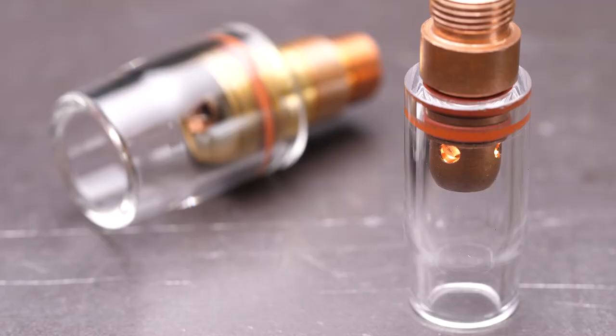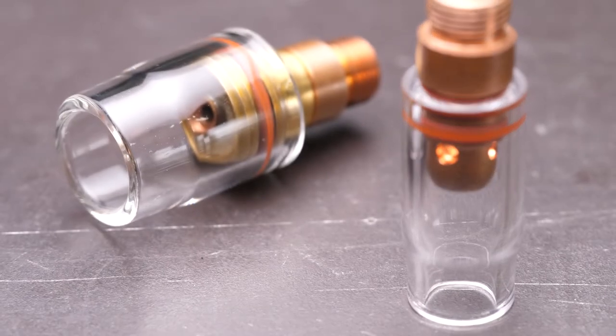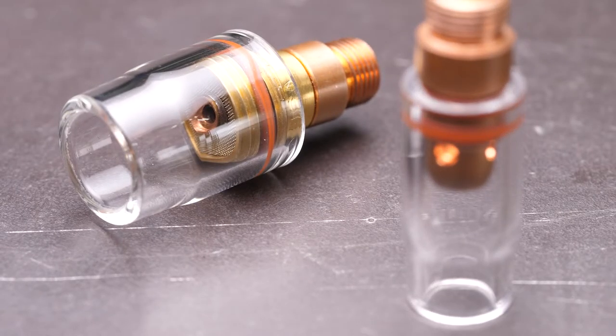If we compare the regular collet body with a number 8 cup side by side with a gas lens fitted with the same number 8 cup, the regular setup will need a gas flow of around 10 litres per minute, while the gas lens setup will do the same shielding job with just 5 litres per minute gas flow. This is going to save you nearly half the costs on your bottle of gas.